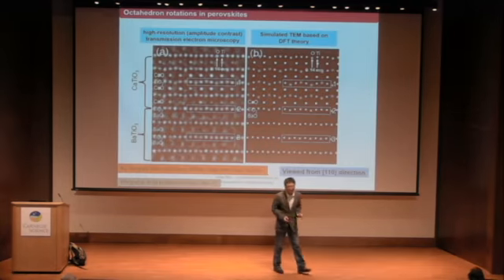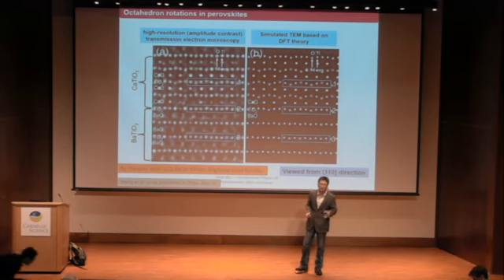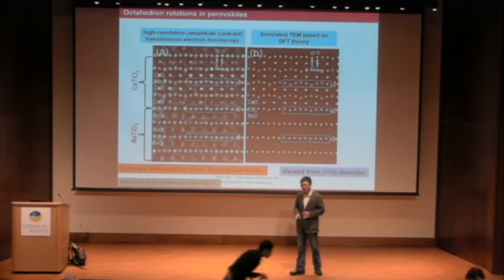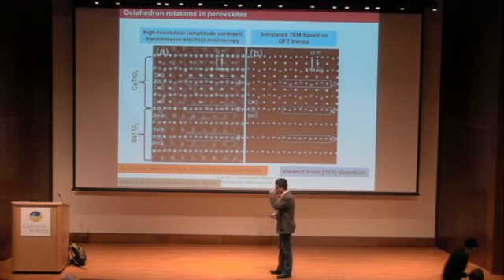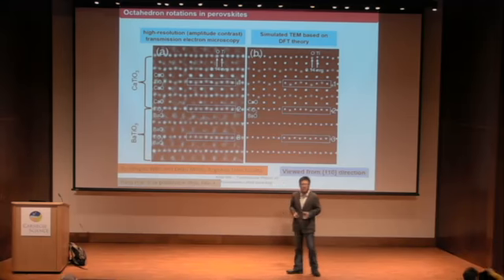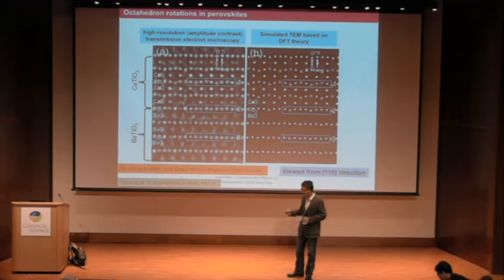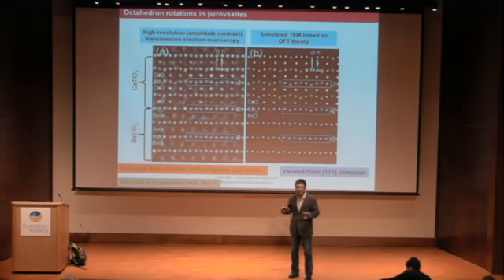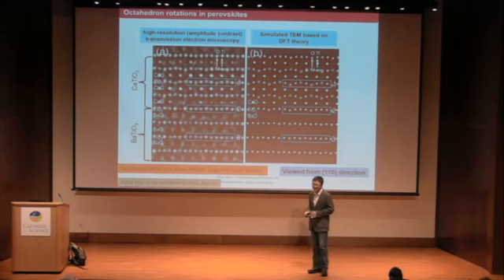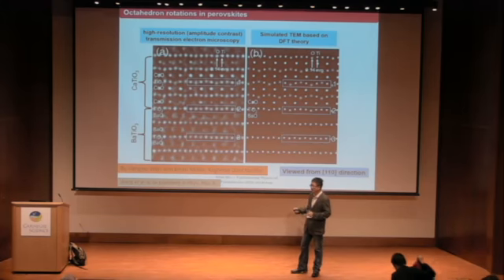Actually, the structure from our calculation is partially confirmed by our experimental collaborators. These experiments by Jianguo Wen and Dean Miller at Argonne user facilities apply this fancy amplitude contrast-based TEM imaging, and they obtained the images.